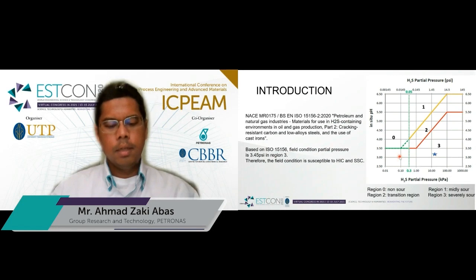Material selection is based on the environment condition and must be carried out according to the guideline given in NACE MR0175 or ISO 15156, Petroleum and natural gas industries, materials for use in H2S containing environments in oil and gas production. Many researchers have reported on the corrosion behavior of carbon steel in high partial pressure CO2 environments, either sweet or sour. But none has reported on HIC and SSC in an environment containing both high CO2 and elevated H2S. For the service to be considered a sour service, the partial pressure of H2S should reach above 0.05 psi.